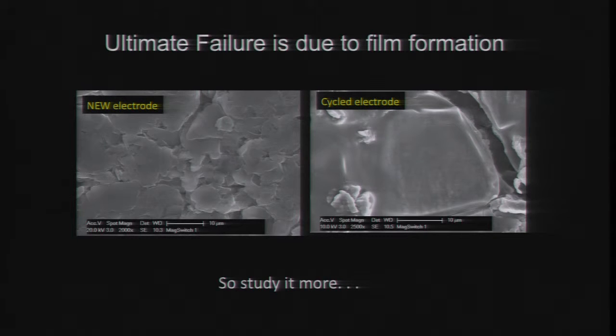This is largely a combination of lithium carbonate and lithium fluoride and lithium hydroxides that gunk up, and they actually disallow the transport of the ions that want to get inside the electrode, and they stop it up. And this is a plan view scanning electron micrograph. So we're looking onto the surface of this electrode, and we're trying to understand, well, what's happening? Is it just getting gummed up from the top or not?